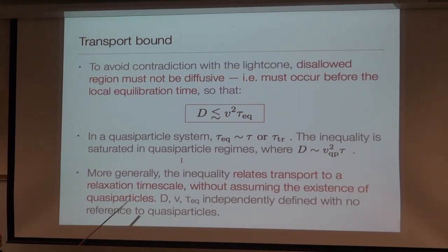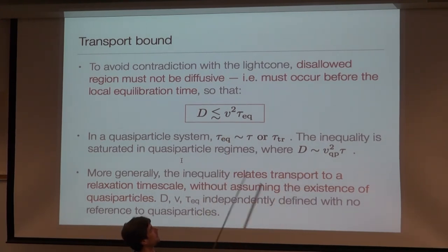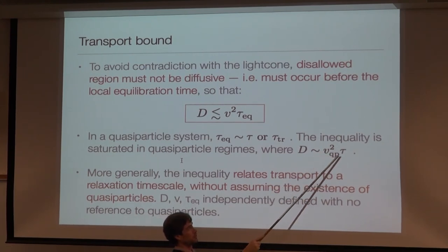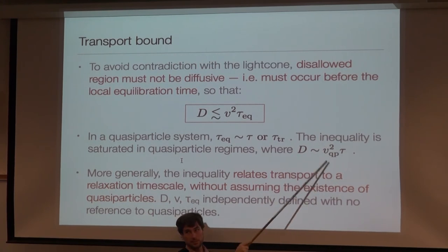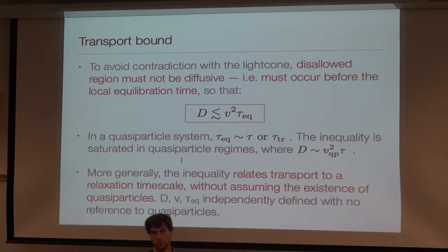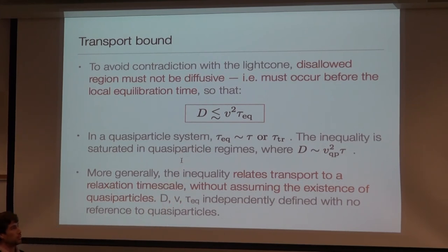In a quasiparticle system, this equilibration rate is typically the quasiparticle lifetime, because you need collisions to locally equilibrate. And this velocity is typically the velocity of the quasiparticles. Indeed, in a quasiparticle system, the diffusivity is the quasiparticle velocity squared times their lifetime. This is the Drude formula in disguise. If I relate this to a conductivity, I get the Drude formula back. So I want to think of this as a generalization of the Drude formula